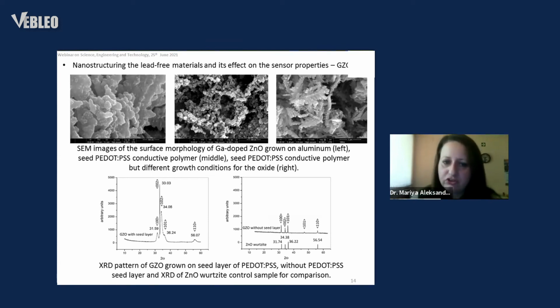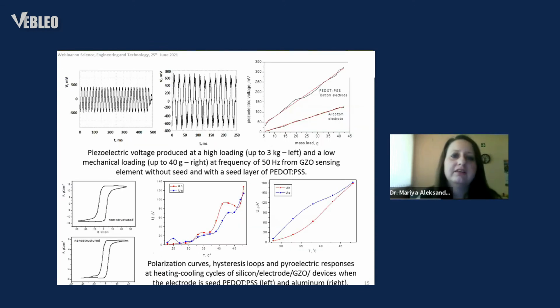of the voltage produced. And here are given some X-ray diffraction patterns that prove that the typical features, if we compare with the standards and with materials without a seed layer, could be formed. And these are typical features, but the strongest is this one at 33 degrees, the 002 plane, which corresponds to a C-axis preferential orientation of the crystallites of the nanodendrites, which is favorable for the fluent polarization.